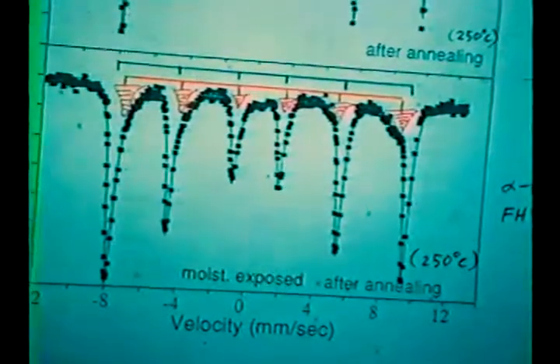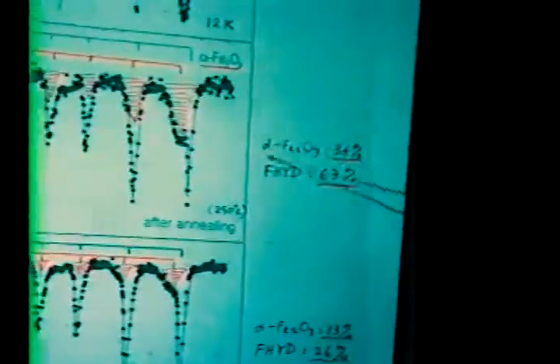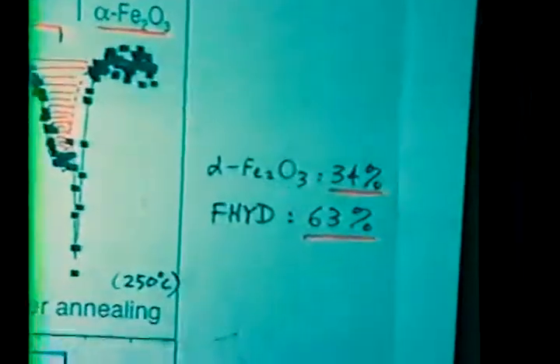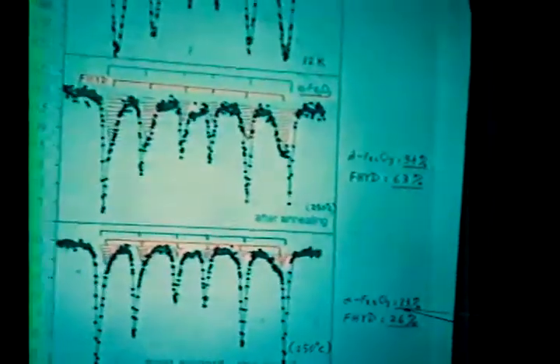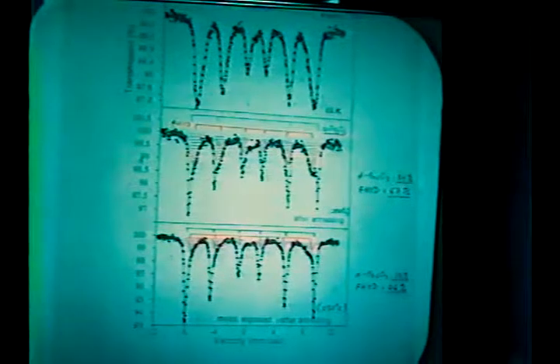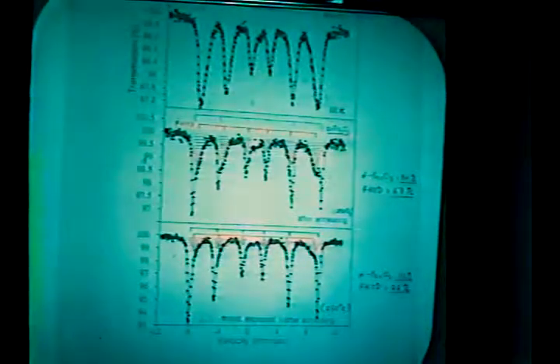The fitting results tell us if it's a fresh sample, hematite is only 34%, and after air exposure the hematite increased to 73%. So it means water really accelerates the formation and agglomeration of hematite, resulting in the loss of surface area.